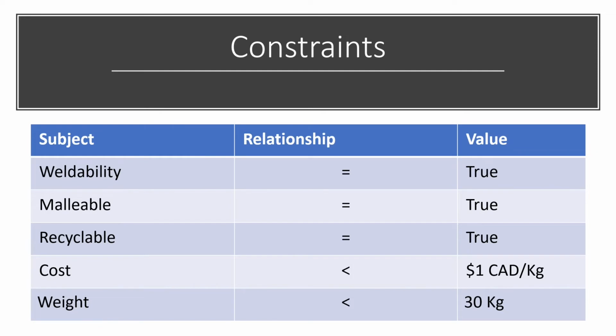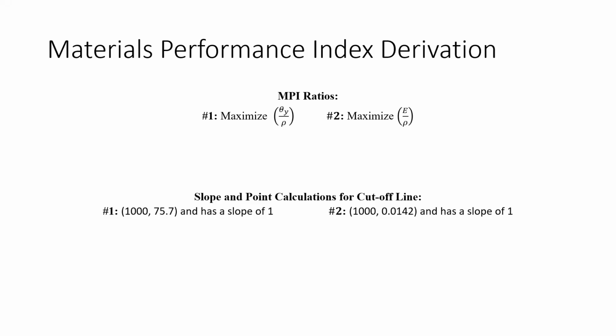For constraints, the material must be weldable, malleable, recyclable, and cost less than $1 Canadian per kilogram, and the 0.3 meter beam must weigh less than 30 kilograms. Two MPI ratios that were derived using those requirements were yield strength over density and Young's modulus over density, both of which we wanted to maximize. We then found the slope and points on each of the MPI cutoff lines. A more in-depth derivation of the MPI ratios can be found in the supporting document.